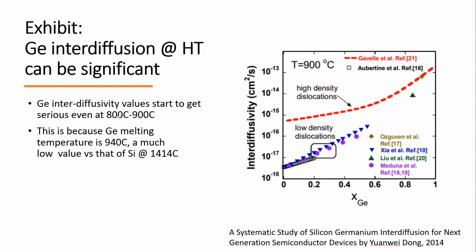It's because the germanium interdiffusivity value is getting serious, right? This number gets serious at this level when your temperature is 800 to 900 or higher. And so this will give you problems. Germanium interdiffusion at high T can be very significant. The reason is that germanium's melting temperature is quite low. It's about 500 degrees lower than silicon. Silicon is 1414 Celsius, and germanium is 938, close to 940 Celsius. This means that germanium can move around freely at lower temperature. At 900, you can imagine the alloy inside is going to be a liquid, depending upon your germanium content. So it's very tricky to avoid this problem.